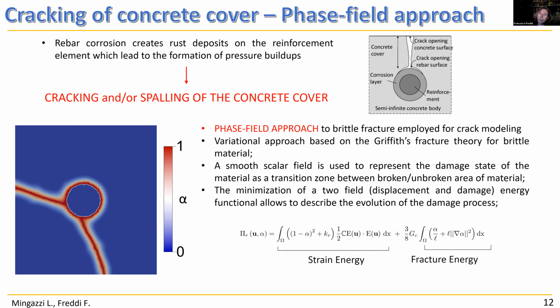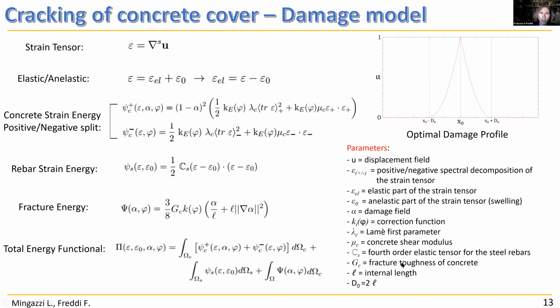Just a second field is introduced that defines the state of the material. 0 is sound, 1 is completely broken, and there is a sharp transition between the two, and this red portion is the crack. So the solution is obtained as a two field functional composed by two energy terms, one associated to the strain energy density of the material and the other associated to the fracture energy of the solid, of crack, sorry. These are the ingredients of the recipe for the phase field approach to fracture.